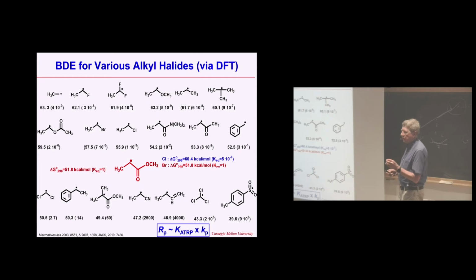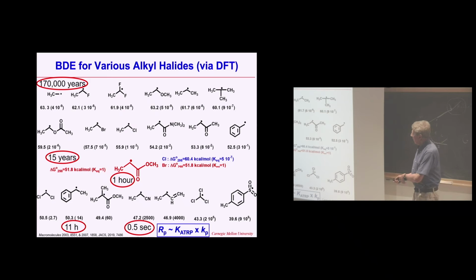Probably more important is not only the equilibrium constant or bond dissociation energy, but also how fast propagation would occur. So it would be a product of the equilibrium constant and the rate constant of propagation. So if under some conditions I have the same catalyst, same reaction temperature, everything identical, if I would polymerize methyl acrylate within 1 hour, I would need 11 hours for styrene. I would have half a second, nearly an explosion, for acrylonitrile. It would take me 15 years for vinyl acetate and 170,000 years for ethylene, which means obviously I cannot use the same catalyst. I need to change the catalyst and I need to develop new catalytic systems which are billion times more active.